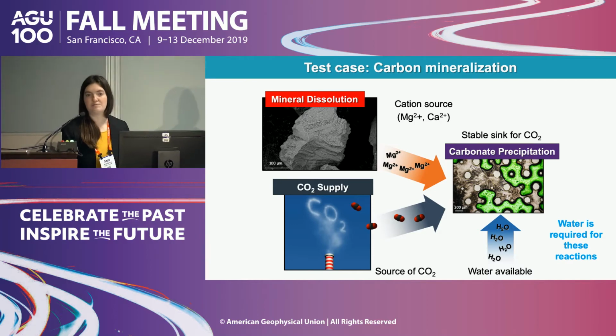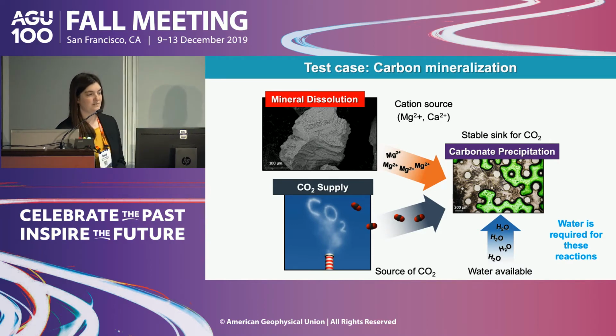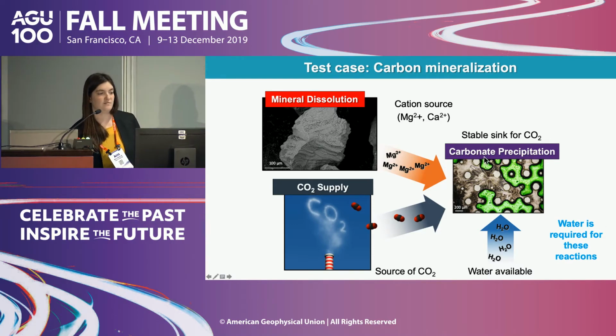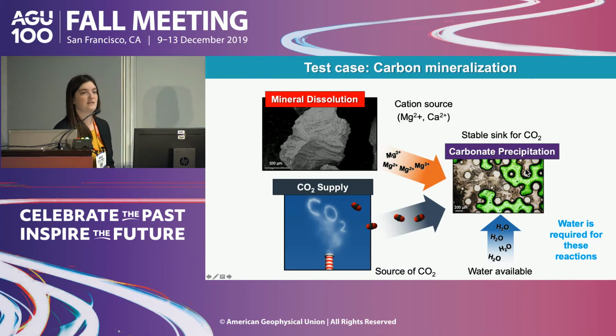So overall, carbon mineralization involves three main steps. It's the dissolution of alkaline earth metal-bearing silicate or hydroxide minerals, which releases cations like magnesium to solution. These cations then react with dissolved CO2 to form carbonate minerals that act then as a solid sink for CO2 that's stable over essentially geologic time.